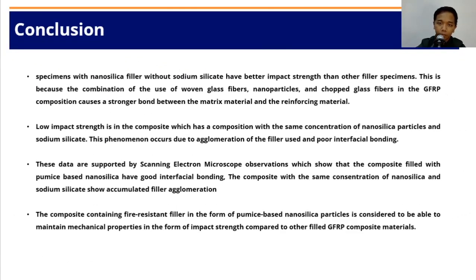Okay, the last part of this presentation is a conclusion about the research. From the research that has been done, it can be concluded that the impact test results show that the specimen with nanosilica filler without an additional sodium silicate has a better impact strength than the other filled specimens.